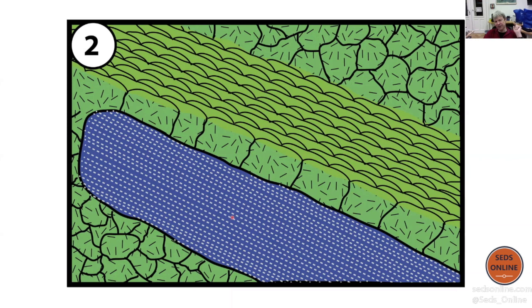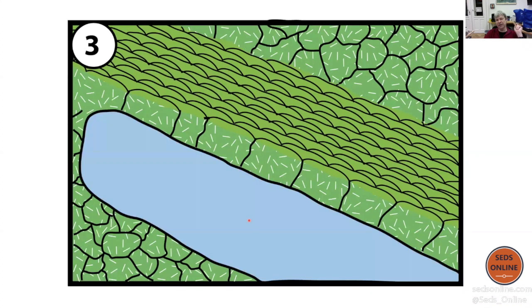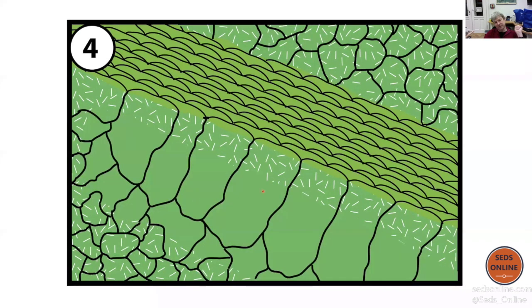The next step then is dissolution of aragonite, which means this shell will be dissolved and the aragonite needles will be dissolved. So we get our pitted microspar and here a moldic pore, a dissolved shell. And then the cementation continues. And this is what we see. One crystal is prism, pitted microspar, and recrystallized shell all at once.